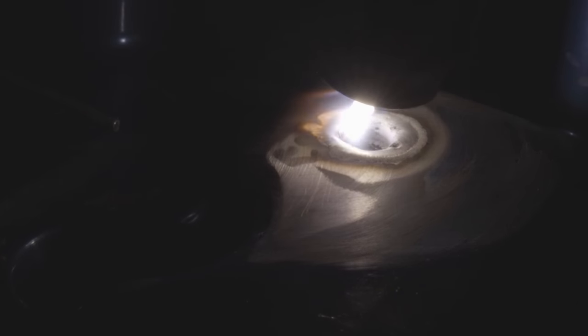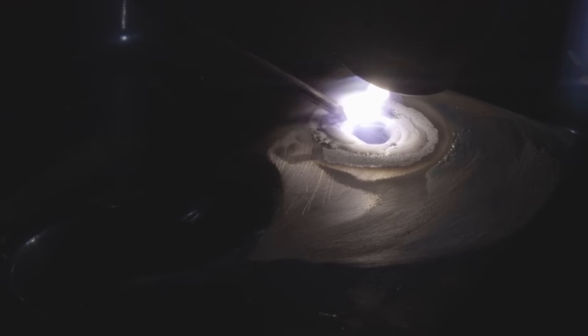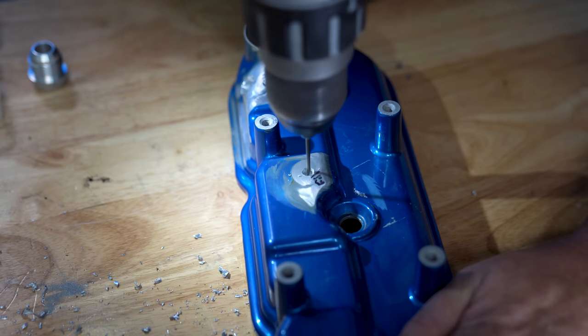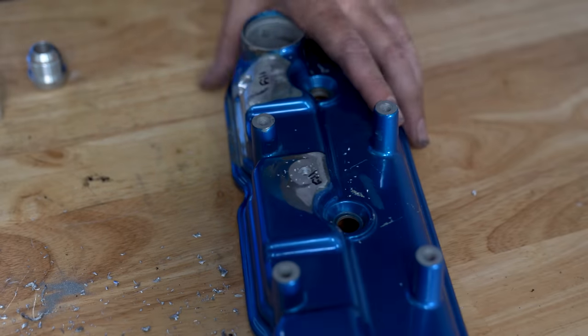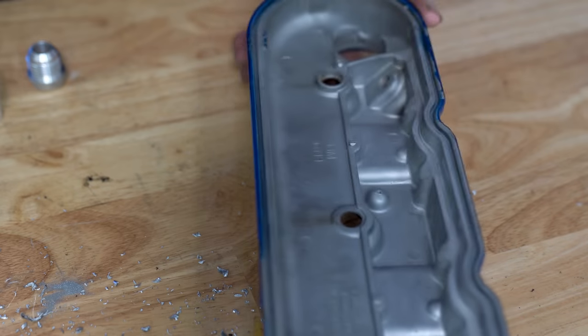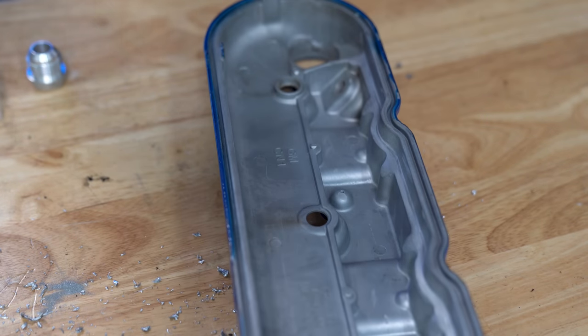The result is a fisheye that forms on the top of the weld. Aside from being really pesky to chase out, you'll actually spend more time dealing with either adding way more filler to it, which takes way longer to grind down and finish, or you'll grind and finish enough to where you have to go right back over and weld it back up again. All of this extra work is more time than it takes to drill a tiny relief hole through the valve cover before you weld it.